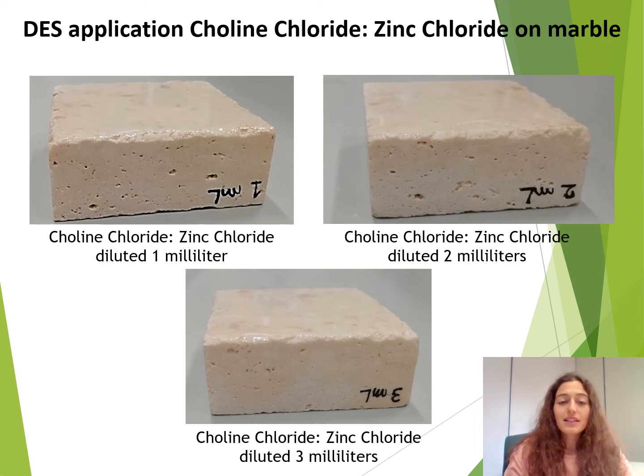From the excellent results obtained, choline chloride zinc chloride diluted with 1 ml, 2 ml, and 3 ml was applied on white marble specimens to know their behavior. They were applied with a spatula on the marble specimens and left to dry for 24 hours. After 24 hours, it was observed that the solvents diluted with 1 ml and 2 ml did not dry out and absorbed water. The deep eutectic solvent diluted with 3 ml did not dry but did not absorb water.